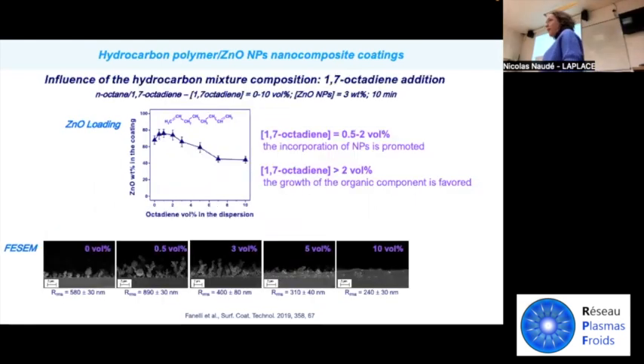There is in principle another way to change the chemical composition of the coatings by acting on the composition of the liquid precursor of our dispersion. For instance, in our work, we used a mixture of normal octane and 1,7 octadiene. So we tried to investigate the influence of the concentration of octadiene in the mixture. Of course, the presence in these molecules of two terminal carbon-carbon double bonds could lead to an enhancement of the growth rate of the organic component.